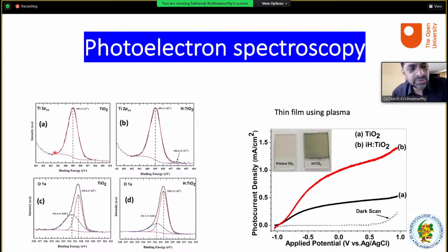You can see a new peak. This is nothing but titania 3+. So this is very much research, you need to focus on small things. Look at this. If I had given this to you normally, you would not find anything. You would say, sir, there is nothing there. But if you look more in depth, this small peak makes such a big difference in the activity of the system. That is titania 3+. This titania 3+ is responsible for the photocatalytic activity. Okay, without it there would be no catalytic activity.